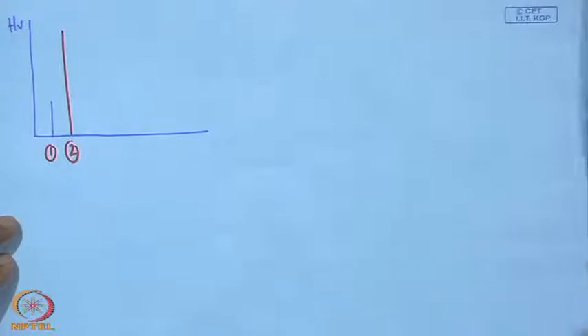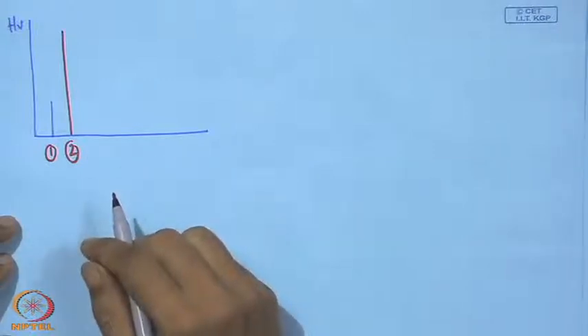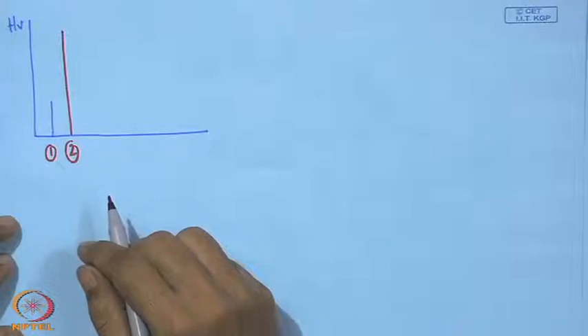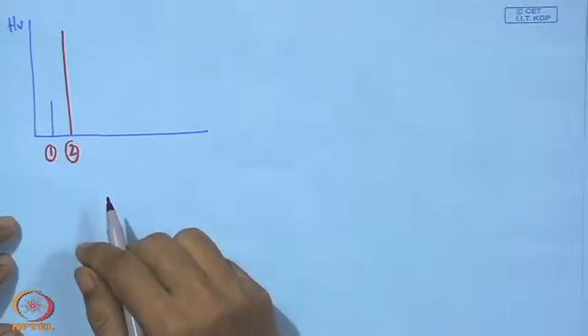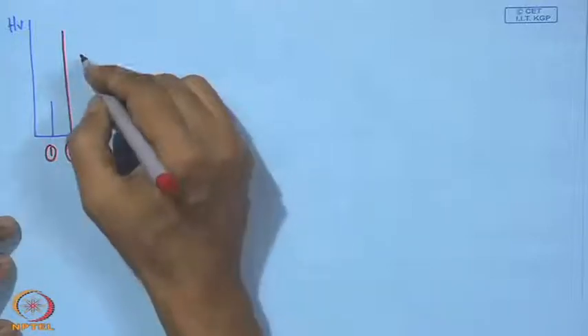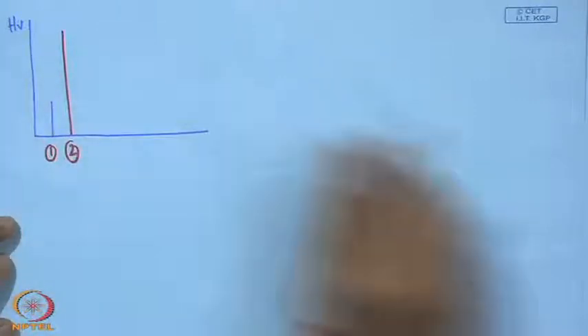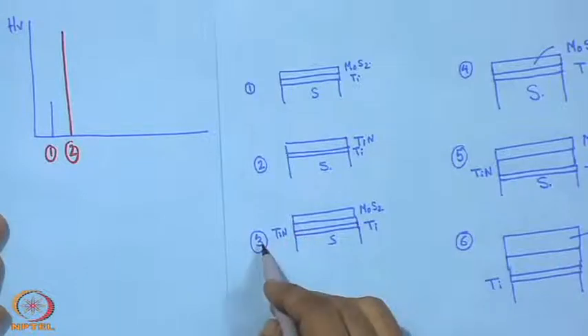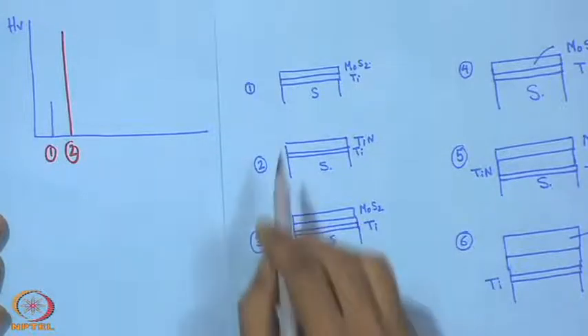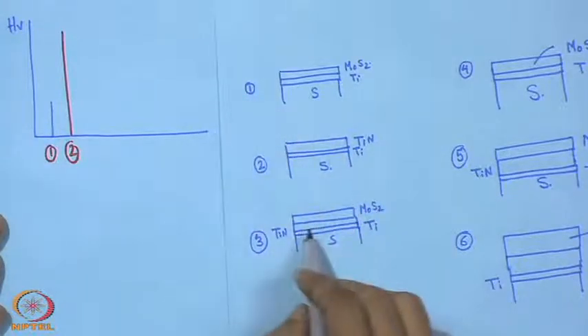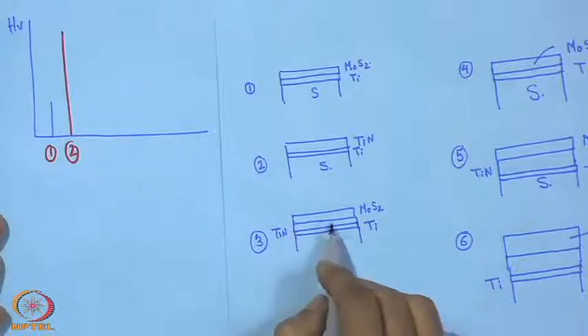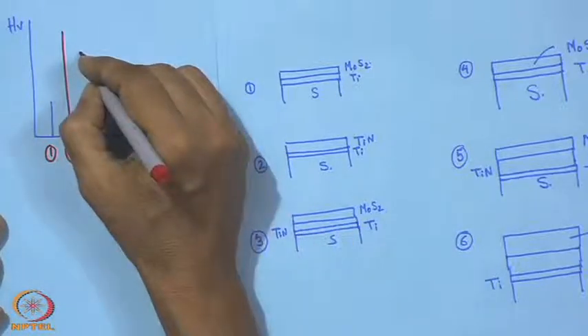followed by number 3, and this number 3 is actually MoS2, which is supported by this TiN. So, its hardness will fall, but we can see the bulk hardness of these three will be more than that of 1, because here we have a support of TiN. So, that will be somewhere little below this one.